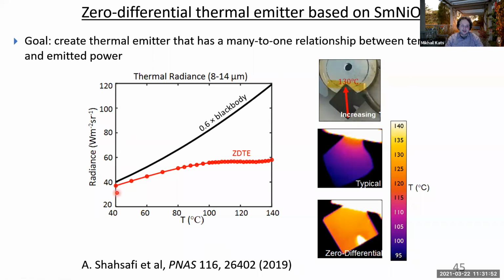This is the integrated radiance, integrated over wavelengths, versus temperature. You see this range over here for the zero-differential emitter, this surface with samarium nickel oxide on top of sapphire, where the curve is flat. This is what we were looking for, the radiance which doesn't change with temperature. You can see evidence of this with infrared imaging. For example, if you have a sample that's just hanging off of our temperature chuck, over here it's at 130 degrees, and over here it's at a much colder temperature, about 90 degrees, just because it's hanging off the chuck and air cools it down.